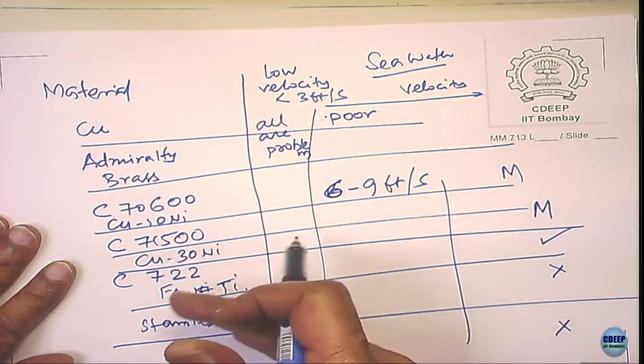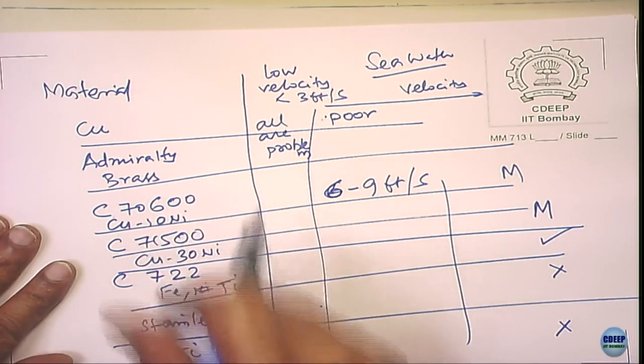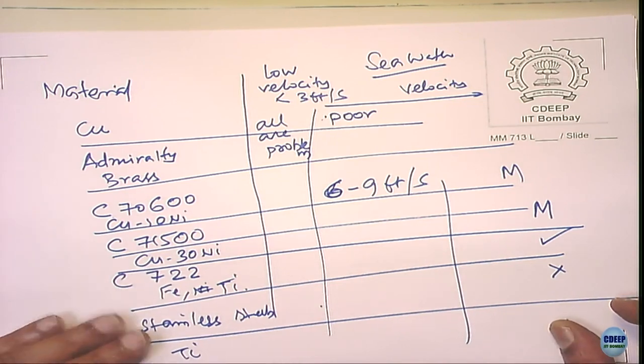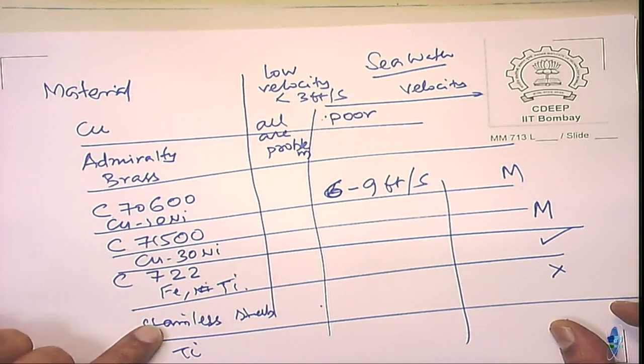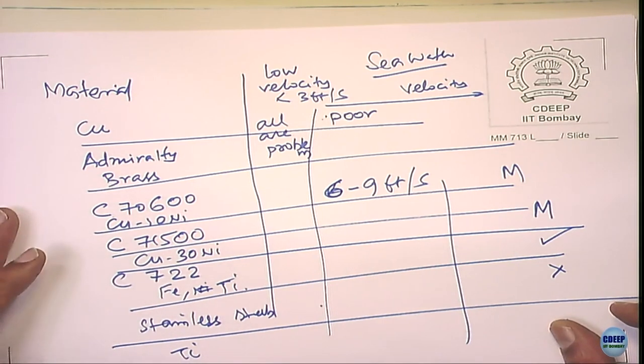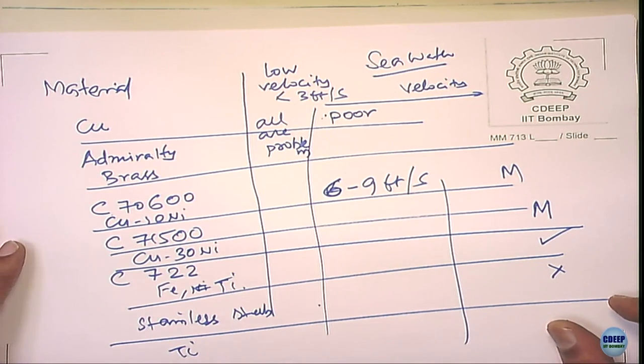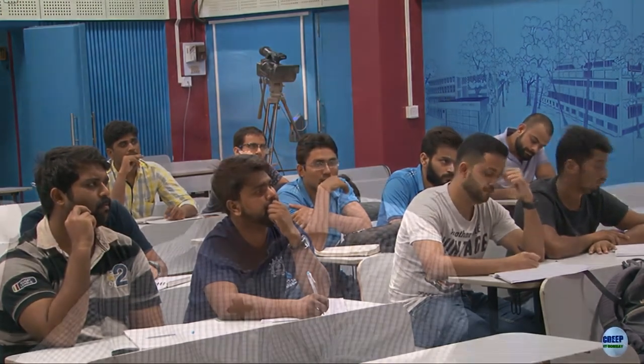So higher velocity means stainless steels and titanium alloys. These are the ways that you can use it. But titanium alloys can be used, but the stainless steels of all categories cannot be used in seawater application, right? There are some problems. What is the problem there? We use a stainless steel in seawater application. What is the problem? Yeah, it could be pitting corrosion, crevice corrosion. So you can only use highly alloyed stainless steels like super duplex or hyper duplex stainless steels, or go for super austenitic grade stainless steels.